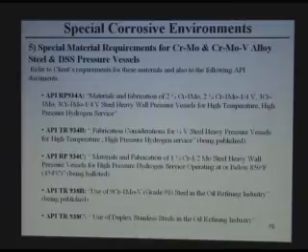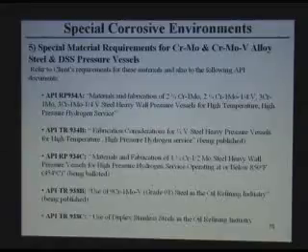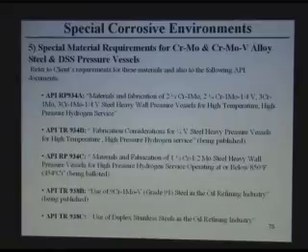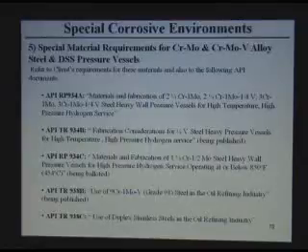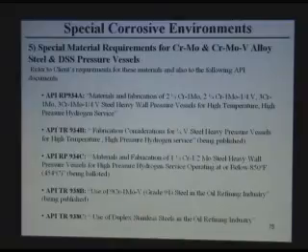This material is used mainly for hydrotreaters of naphtha, not high-pressure, diesel type hydrotreaters. These are more heavy oil type reactors and hydrocrackers. This document is a report about Grade 91 steel, on how to weld it and how to specify it. It was a big problem to control the welding of this material because it tends to become very hard and tends to crack. So this report gives some indication of how to do it.